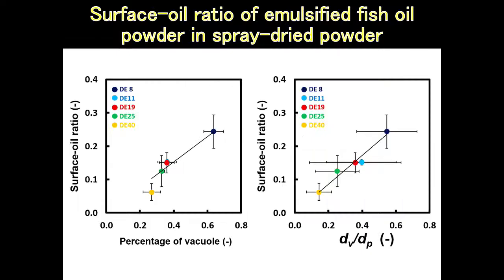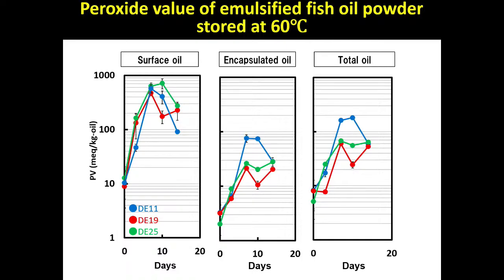And then, high vacuole powder has a high surface oil ratio. And this is dV by dP, the average vacuole size divided by powder size. A high vacuole size means a larger amount of surface oil. So this is the storage days, at 60 degrees Celsius. We store at 60 degrees Celsius.